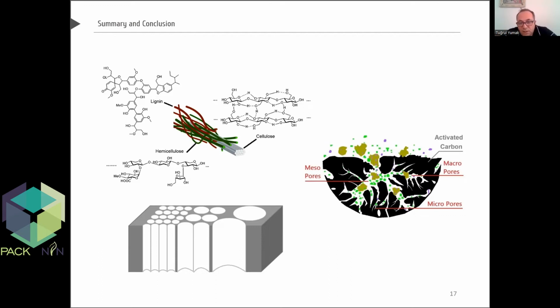The second one is the energy density. Even though the specific capacitance of the biomass-derived or biomass-based activated carbons can reach relatively high values, above 400 farads per gram, they are still not comparable to the pseudocapacitive materials, which can reach specific capacitance above 1000 farad per gram. Maybe heteroatom doping such as nitrogen, sulfur, boron, or oxygen, or nanocomposites of biomass-based carbons, and maybe coating with conducting polymers and metal oxides, may help to increase the energy density.